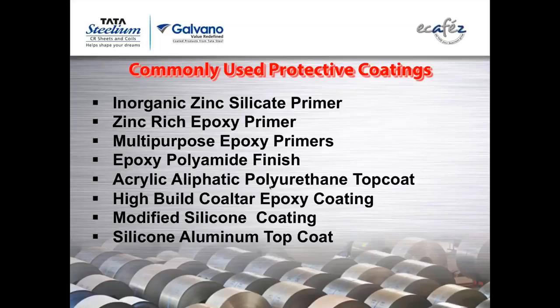Then aliphatic, we are talking about the isocyanate. You can have aliphatic isocyanate as well as aromatic isocyanate. Now aromatic is something with a benzene ring. Aromatics are not stable. Aliphatics are stable. So naturally, if you use aromatic isocyanate as hardener, it is going to fail prematurely. Sometimes if you have white finishes, it may turn yellowish and then fail. So usually for good outdoor resistance, you have to specify acrylic aliphatic polyurethane top coat.